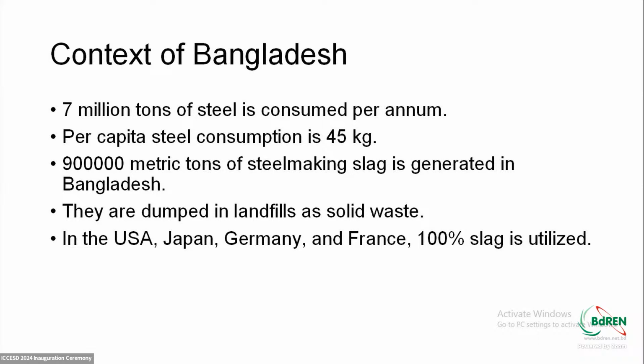So our focus was: what is the condition in Bangladesh? We chose one particular steel mill, and used slag from different production periods. We tried to characterize the chemical composition, and tested the slag for clinker replacement and aggregate replacement.